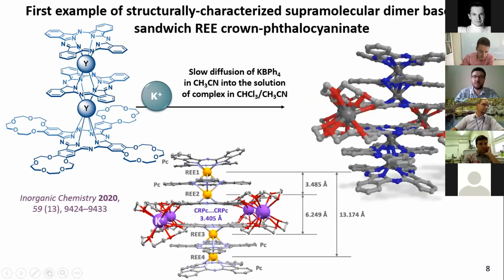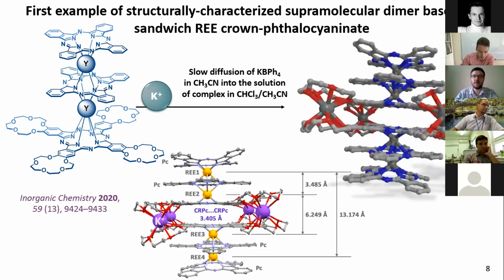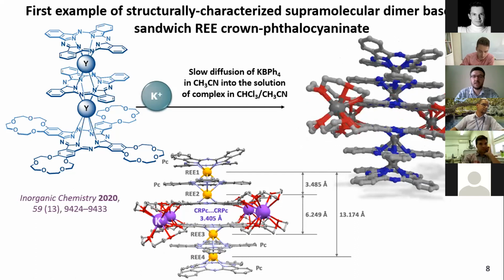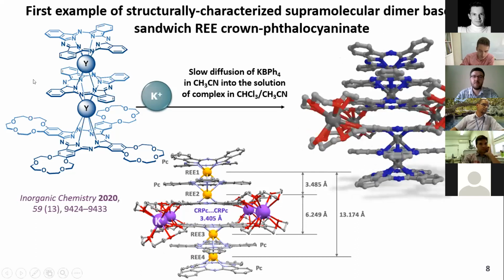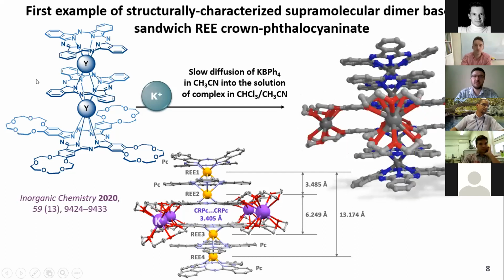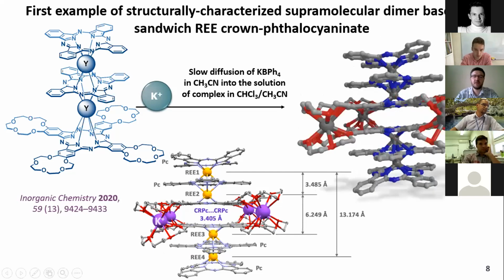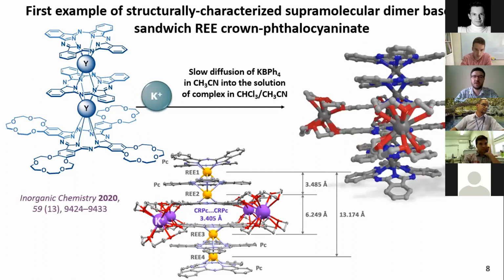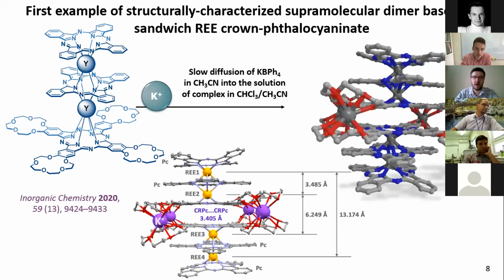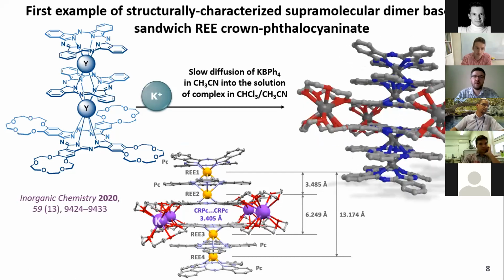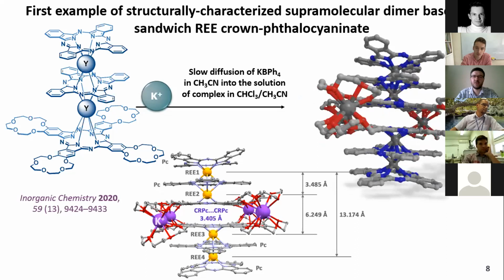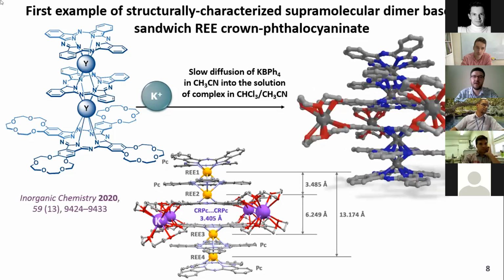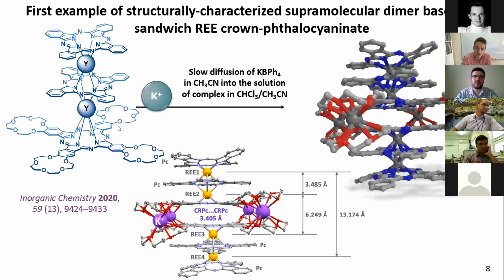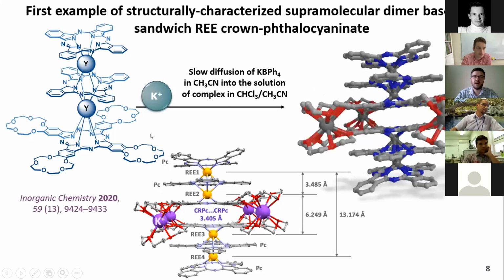These molecules can be interesting objects for studies of long-distance magnetic interactions. But the problem with exactly this complex is that it's not very easy to separate it from the reaction mixture, to separate it from other possible triple deckers which form in this reaction. And moreover, it turned out not to be as stable as we expected. During several months in aerobic atmosphere, it slowly decomposed with the formation of double decker and metal-free ligand.